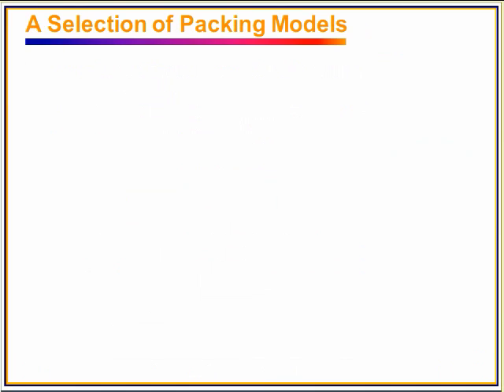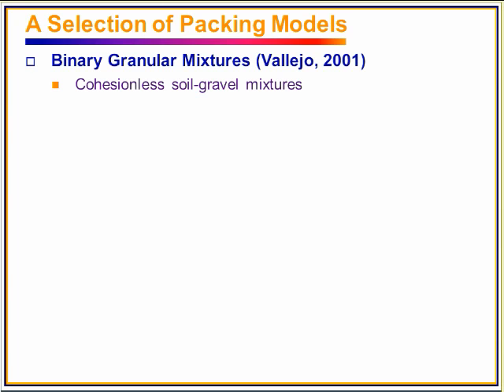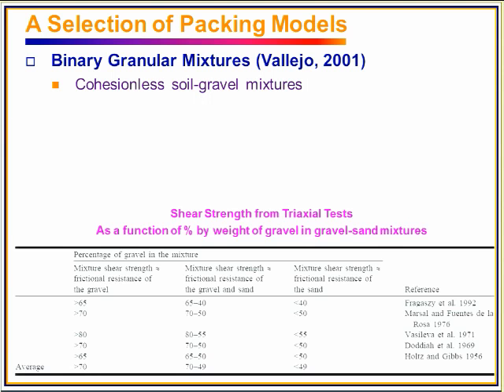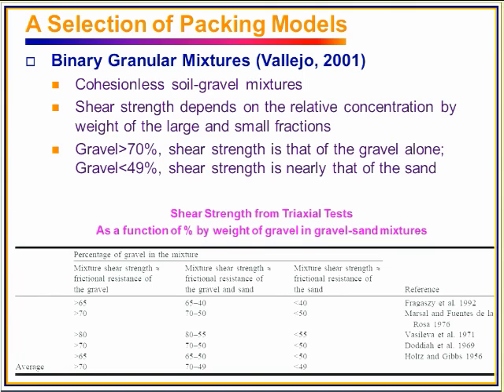In addition to those gradation quantification methods, there are a lot of packing models to describe aggregate packing. For example, in geotechnical engineering, for cohesionless soil-gravel mixtures, there are a lot of triaxial shear strength test results. This table shows the shear strength as a function of percent gravel by weight in the gravel-sand mixture. As you can see, when the gravel fraction is greater than 70% by weight, the shear strength is mainly controlled by the gravel. If the gravel fraction is less than 49%, then the shear strength is mainly controlled by the sand fraction.